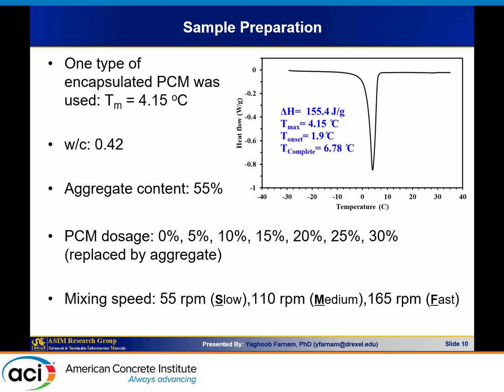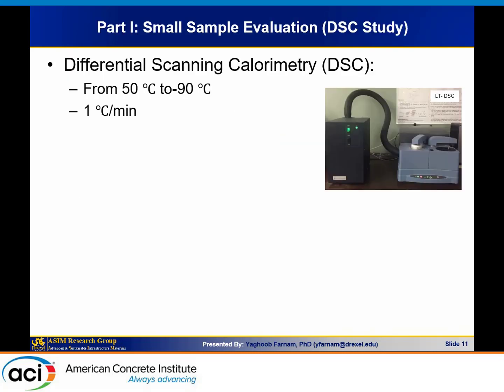The PCM that we used had about 155.4 joules per gram of latent heat of fusion. And then we didn't change the water to cement ratio. That was not the goal of this research. We kept the aggregate content constant at 55%, and we started replacing that 55% by 5%, 10%, 15%, and 20%, up to 30% replacement of the aggregate, using PCM. And then we had three types of mixing speed: slow, medium, and fast. We wanted to see the effect of aggregate and the mixing.